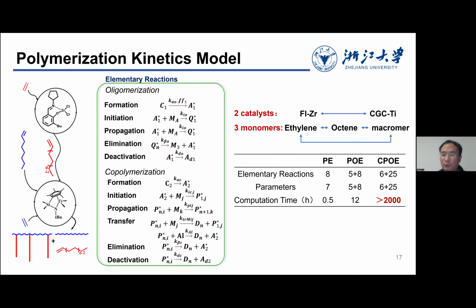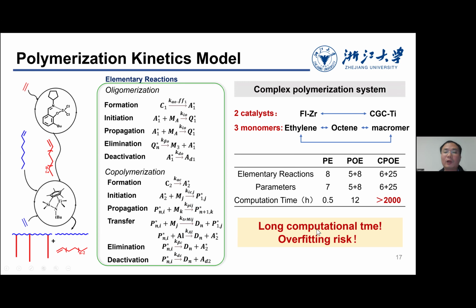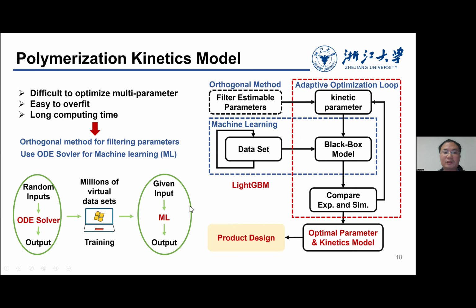And we find that this process is pretty challenging. The reason is because we have 3 monomers and 2 catalysts in this system. If we write the kinetic reactions out, we find we have almost 31 parameters for the calculation. That means our computation time will exceed 2,000 hours, and there is also a risk of overfitting. So we developed a method